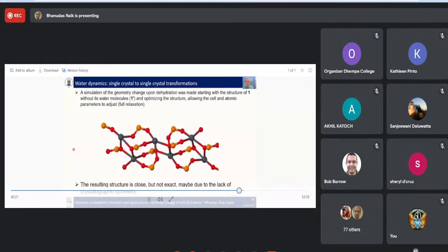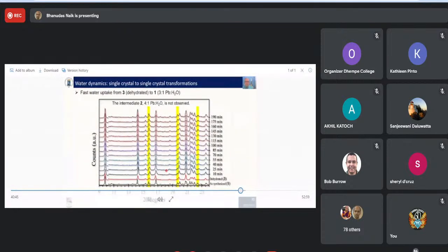But the idea is that now we've closed up this distance here, this oxygen-lead bond has now formed, and this one in the bottom here as well. And we can see this fast uptake here between 3, which is the anhydrous, and 1. This intermediate with the 4 to 1 is not even observed because it has such a very fast lifespan.